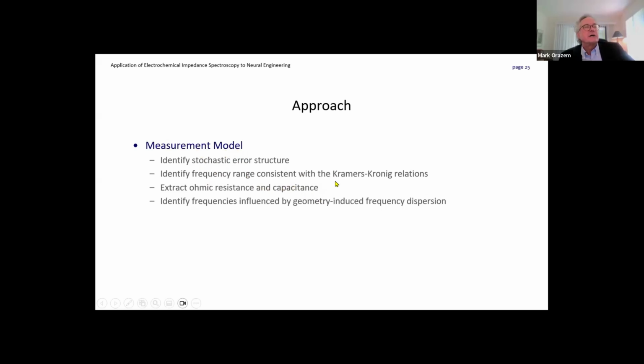We use this to identify the frequency range that's consistent with the Kramers-Kronig relations. We use this to extract the ohmic resistance and capacitance, and this allows us to identify the frequency that's influenced by the geometry of the electrode. And then we focus on a process model, and this is what we're doing to try to extract physically meaningful parameters. And the key thing I want to emphasize in this presentation is the estimation of the capacitance.